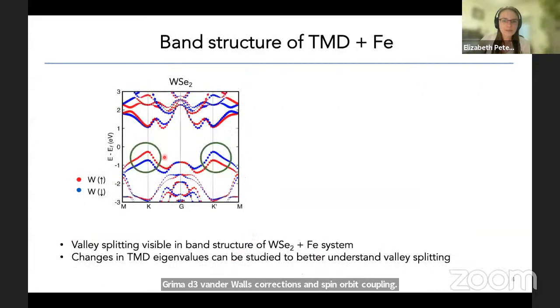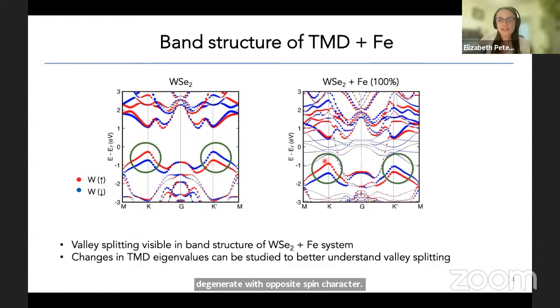Okay, so going back to the band structure of the transition metal dichalcogenide, you can see that at K and K prime, the spin orbit split valence bands are degenerate with opposite spin character. When I introduce the iron atom, you see that something clearly changes at K and K prime, and they are no longer energetically degenerate. And this is good because it means that we can track what's happening to these eigenvalues to learn something about the valley splitting at different coverages and alignments.